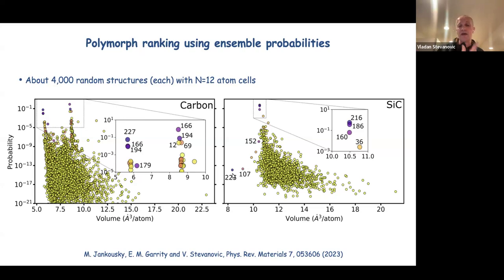What one can do is put enthalpy instead of energy into the Boltzmann exponential and then increase the pressure. And what you will see then is that at a pressure of about 50 or 60 gigapascals, I think, the rock salt will become the most probable structure. And by the way, 60 gigapascals is about the transition pressure between zinc blende and rock salt.